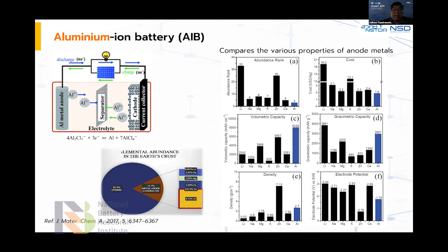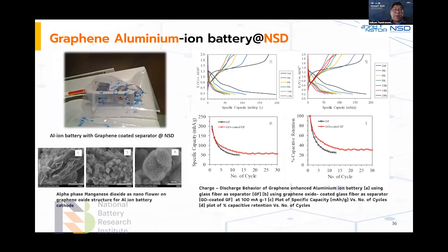But the main burden of this aluminum-ion battery is the electrolyte. That's why we try to solve that problem using graphene. And also, we first demonstrate how to use graphene to increase the performance of the aluminum-ion battery by using graphene coated on the separator. And you can see that we can also use graphene oxide in the alpha phase manganese dioxide in the aluminum-ion battery. And I can show you first the charge-discharge performance of our aluminum-ion battery, which is in the range of about 200 milliamp hour per gram, and also with graphene we can increase the specific capacity and increase the number of cycles, the percent of retention of the cycle.